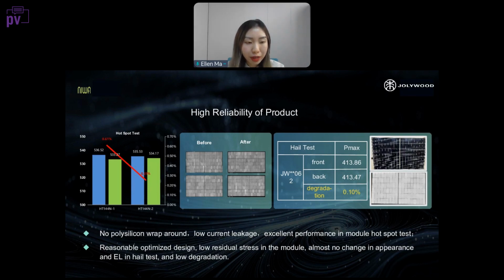And before, we mentioned a lot of things about the hotspot and hail tests. Here we're also doing those 2 tests. For the hotspot test, we can see that the degradation rate is only around 0.6% to 0.25%, and the EL picture before and after the test is almost the same. We also did the hail test. The degradation rate is only around 0.1%, and the appearance and the ELs are exactly the same as before the test.